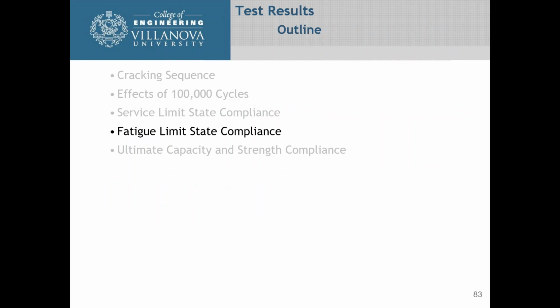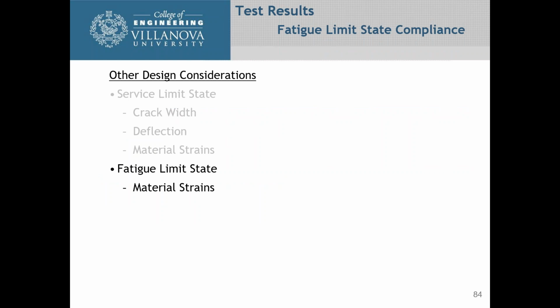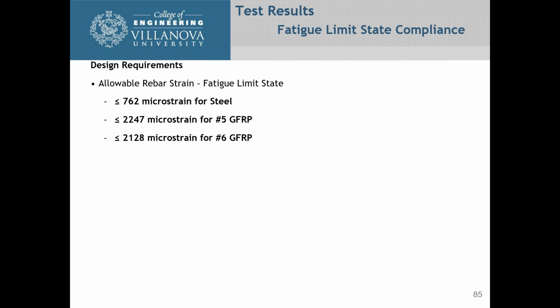So we're going to look at fatigue limit state compliance, and we're going to look at material strains here. Under fatigue for the steel, you had to be less than or equal to 762 microstrains. For the number 5 GFRP bar, it's 2,247, and for a number 6, it's 2128.